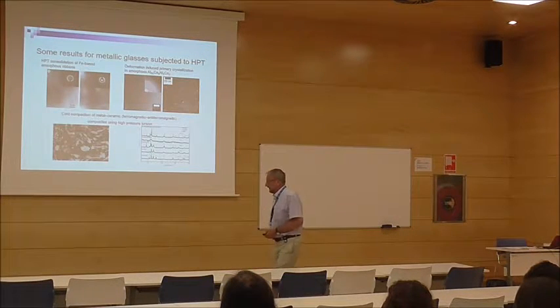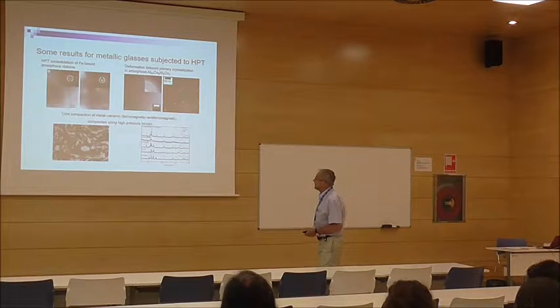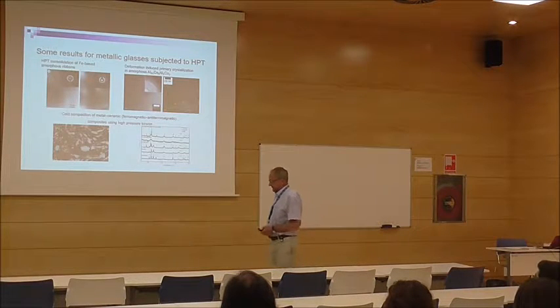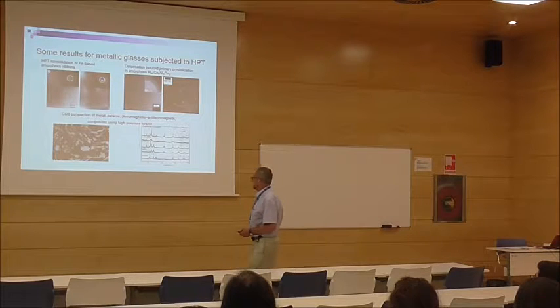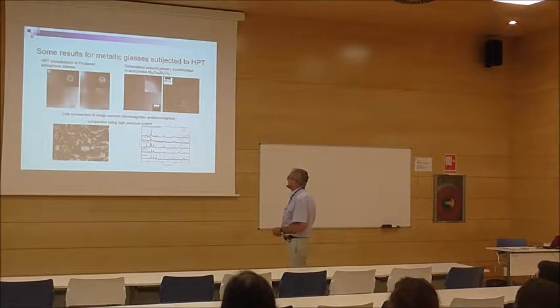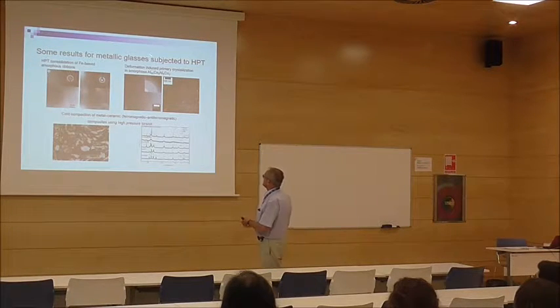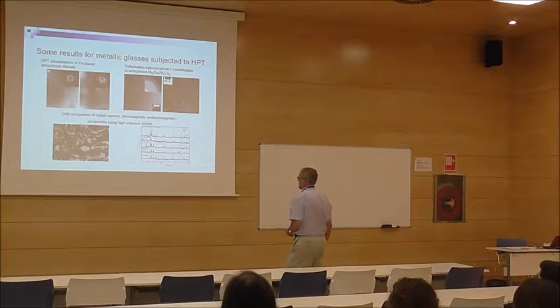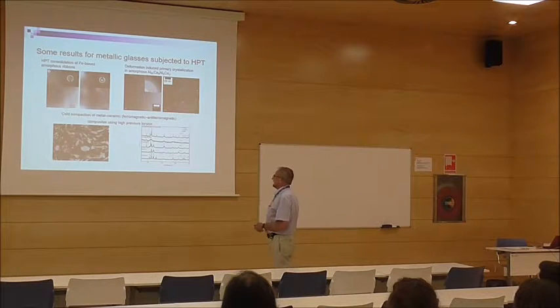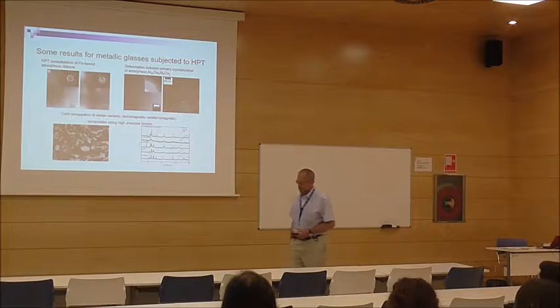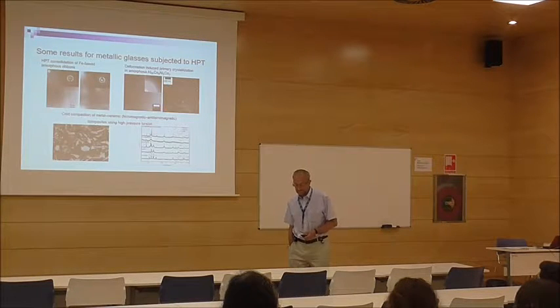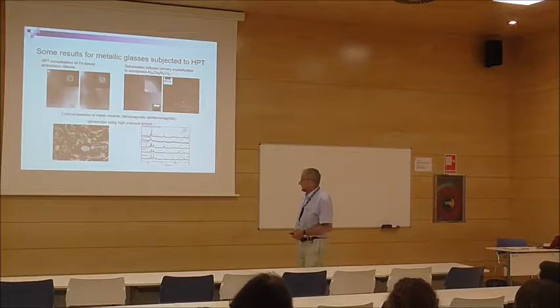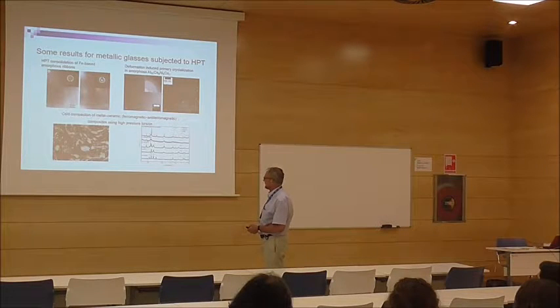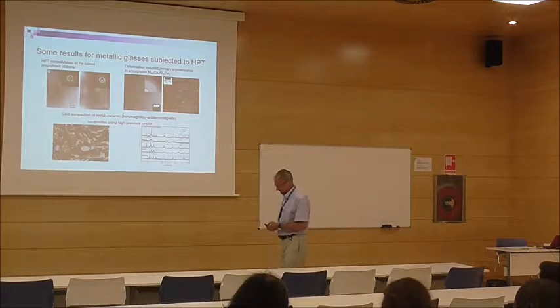And some work was done with a Hungarian postdoc, Adam, on in situ crystallization during HPT in metallic glasses, aluminum-based metallic glasses. And we also did cold compaction of metallic, ceramic, ferromagnetic and anti-ferromagnetic materials by high pressure. This is quite interesting because it was the first time for cold consolidation with a very high strength material.